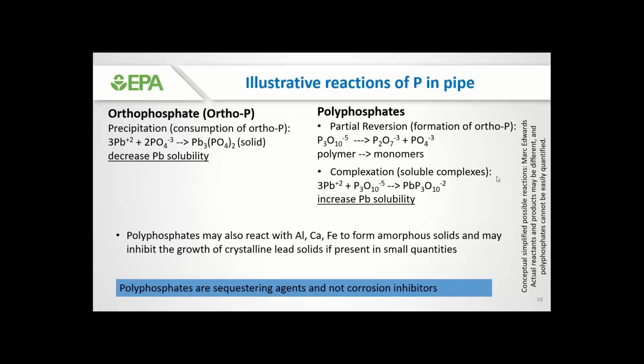Let's go back to the question marks after poly. If we have orthophosphate added to the water, we expect the interaction of orthophosphate with the lead to be something like what I'm showing you here on the left-hand side of the slide. So when we have oxidized lead being leached into the water, the idea is that orthophosphate will precipitate that lead out of solution by forming some sort of lead phosphate solid to create a protective scale and therefore decrease lead solubility. When we have polyphosphates in the water, there's two things that can happen.